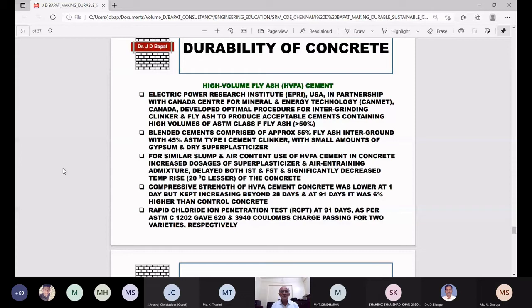Compressive strength of high volume fly ash cement concrete was lower at 1 day, but kept on increasing beyond 28 days, and at 91 days it was 6% higher than the control concrete made from Portland cement. Rapid chloride ion penetration test, RCPT, value at 91 days as per ASTM C1202 gave the value of 620 as against 3940 for Portland cement concrete. So you can see the difference between RCPT values.